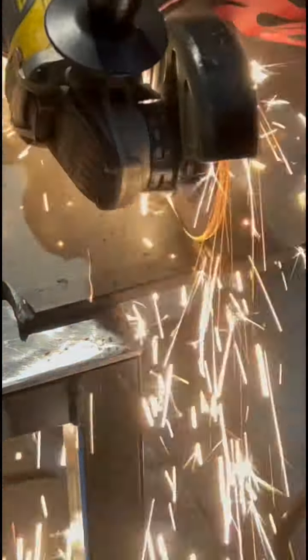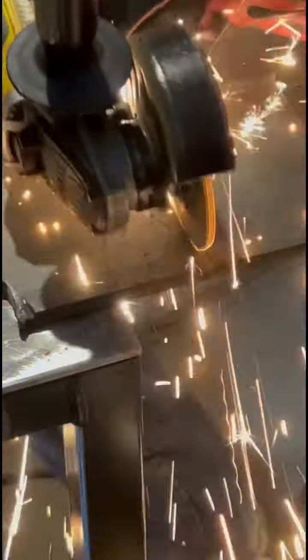It took a little bit more space, and with that 60-10 rod, I am pushing that root in there. My rod is actually contacting those bevels, and you can see there's a lot more action happening on the back side than there is the front side. That's a good thing. That means I'm getting good penetration. So instead of brushing this off, I'm going to grind it down, getting all them wagon tracks out, make sure all that slag's out, that way I don't trap it.